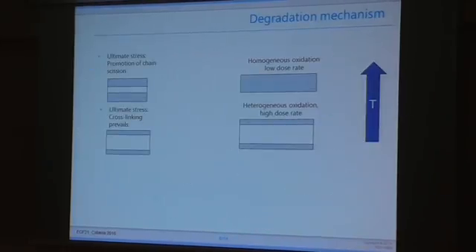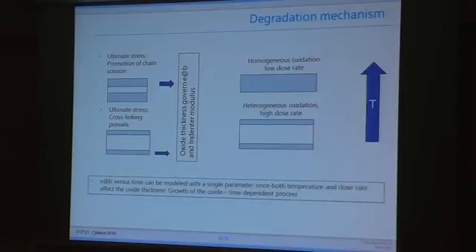What does this mean for our mechanical properties? If we have a thin oxide layer, we will have prevailing cross-linking, and we will have an increase in ultimate tensile stress. If we have a thicker oxide layer, we will have promotion of chain scission mechanisms, and we will have dominance of chain scission. For elongation at break, this means that oxide thickness is what governs its decrease. Also, the same oxide thickness governs the increase of indentation modulus, and that's why we see a great correlation between these two mechanical properties.